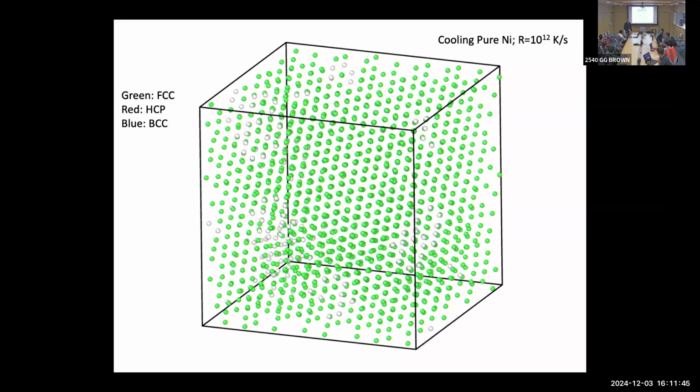It's similar if you're heating, except that it doesn't happen at the same point. That's the difference between liquidus and solidus, and you can keep track of that difference as you tune the rate. If I'm truly in equilibrium, going really slowly, they would occur at the same spot. But because I'm going at a finite rate, it'll be a little bit asymmetric. For this study, I'm not going to deal with that interesting detail. I'm just going to always do cooling, and then it's just this one case.